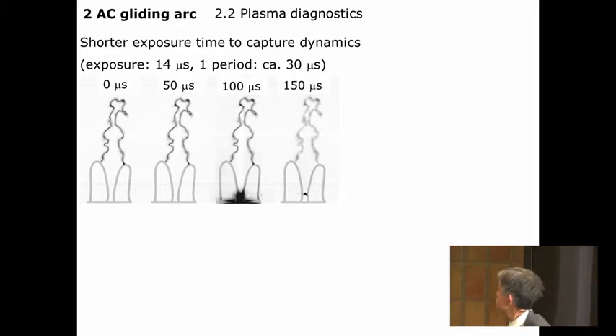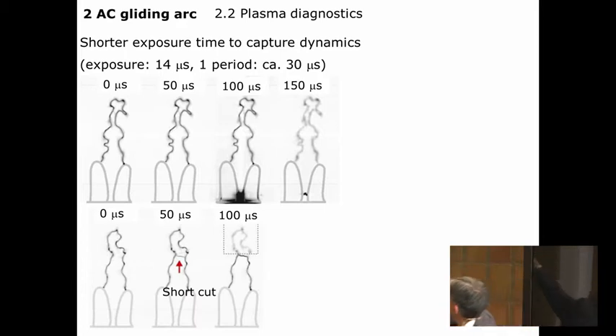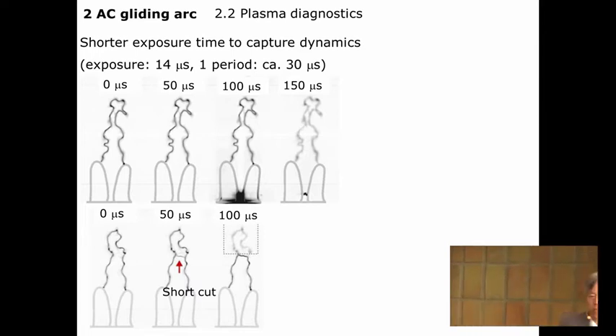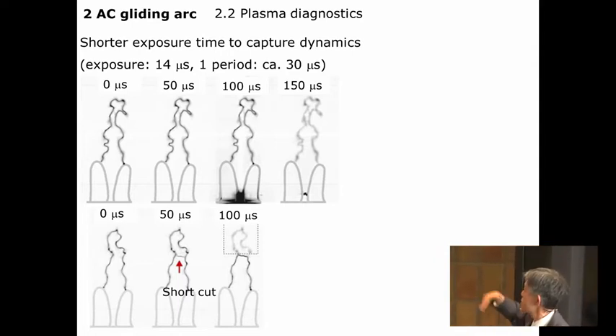And then what was interesting is that plasma can stay there even when the polarization of the voltage changes. Therefore, we saw a kind of fringes of strong emission and low emission in the photo in some cases because of the oscillation of the voltage. And that may be the secret why it can work very well. And then you can get the ignition at some point, then plasma starts to decay. But also something interesting is that in some cases we have some shortcutting events which can shorten the plasma. So it's a kind of very complicated behavior.